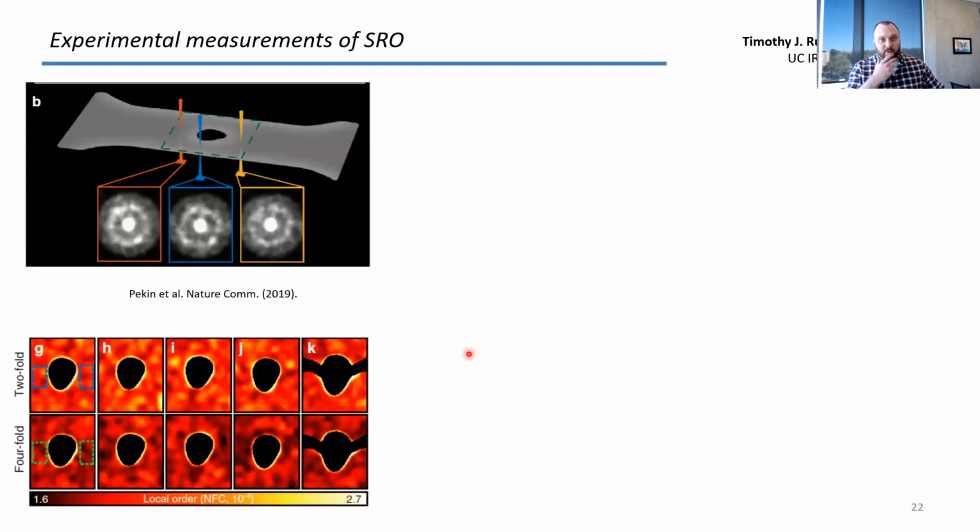The last slide I want to show you is an idea of how we're trying to get at that. It's really hard to measure short range order experimentally. We can't do the same thing we do with our atomistic models, but there's some promising work in the metallic glass field that's motivating and inspiring us. This is one example of nanobeam electron diffraction, an in situ TEM testing of metallic glass samples. What these authors, from Andy Minor's group, were doing is rastering around a stress concentration as they cooled the sample and taking these little nanobeam diffraction patterns.